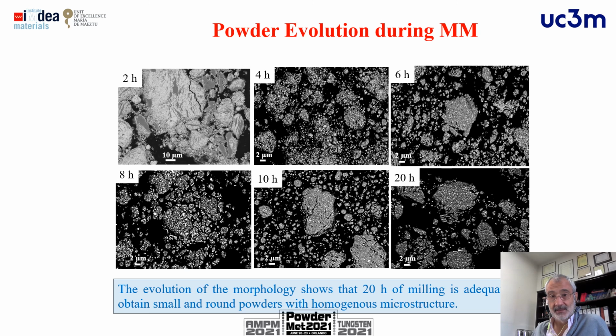In the next slide, we can see the evolution of the morphology of the powders through the milling time, and at the end we have selected the 20 hours milling time in order to have these rounded powders for the consolidation process.